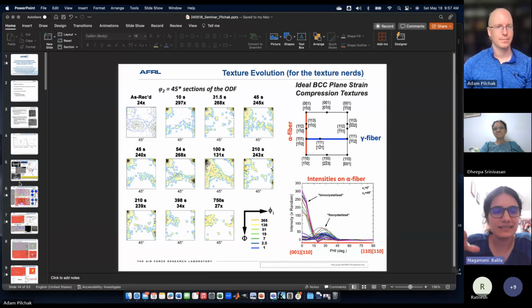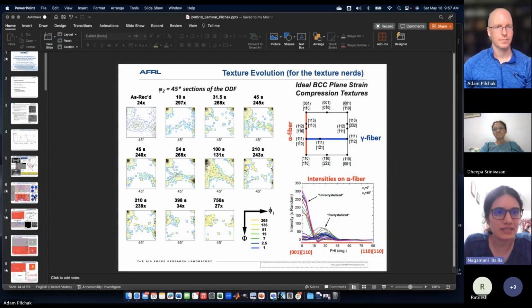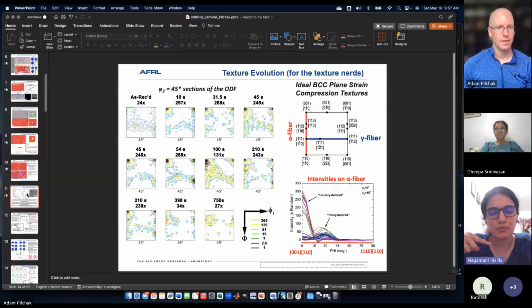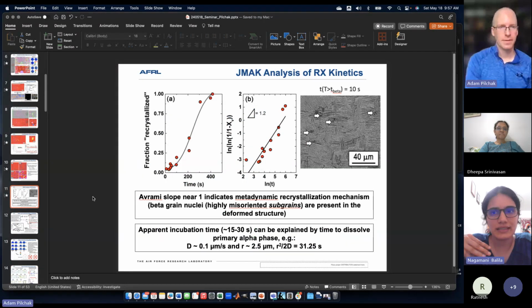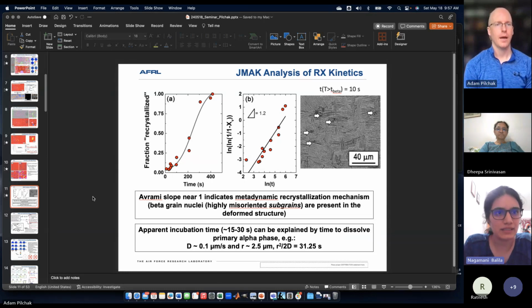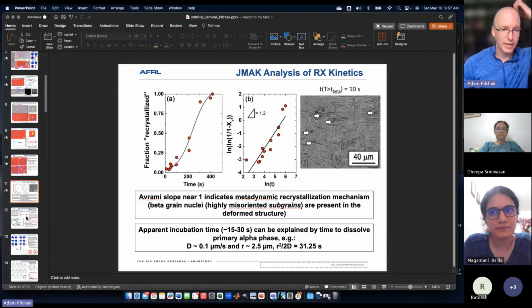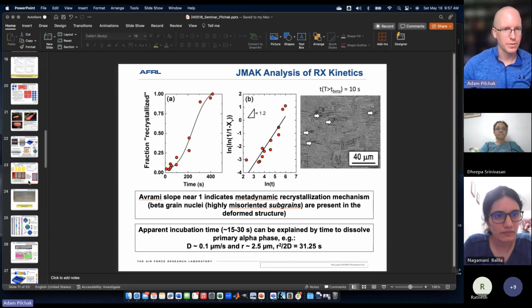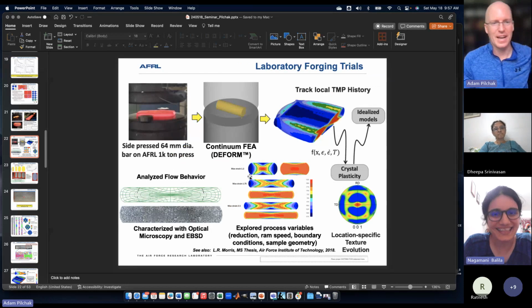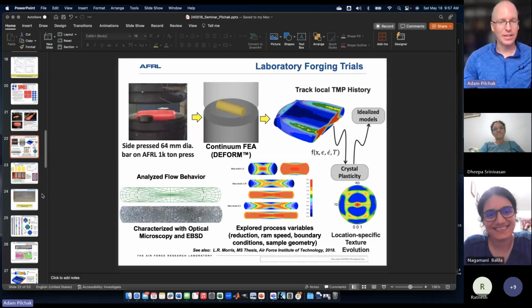So you talked about changing annealing, the time it takes for this transformation to occur in the beta, when you just take it just above the beta transus after the deformation. Did you also change the extent of deformation? I mean, you talked about, of course, the strain path changing, but did the extent of deformation also make a difference too? Yeah, definitely. And I did go over that part too quickly. I'm sorry, I realized I was getting out of time. Thanks for bringing it up because I didn't really say it.